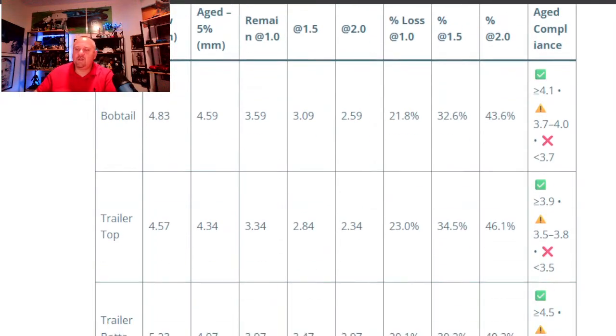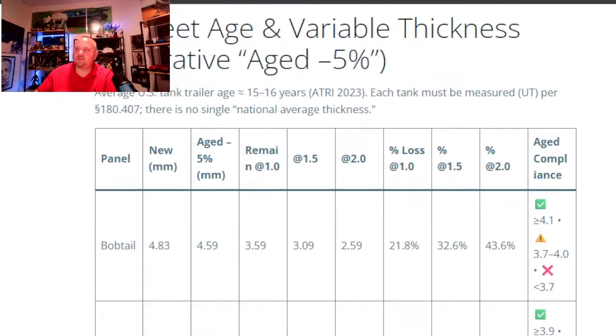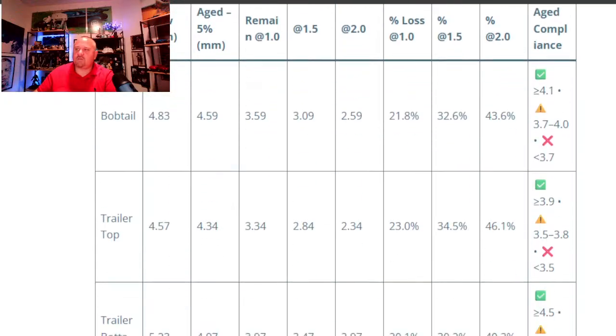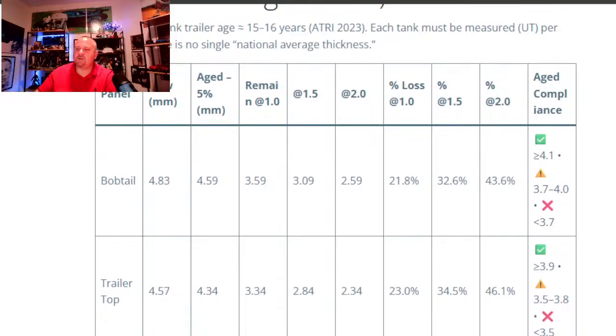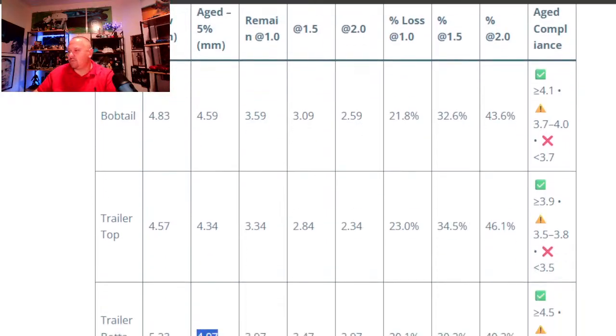Let's look at trailers, tanker trailers. New trailers are 5.23 millimeters, and with age 15 to 16 years old, average thickness is 4.97 millimeters remaining. Now let's look at these numbers. We're at 4.97. That's the average thickness of a 15 to 16 year old tanker. If you come over here, anything less than 4.1 millimeters is out of compliance.